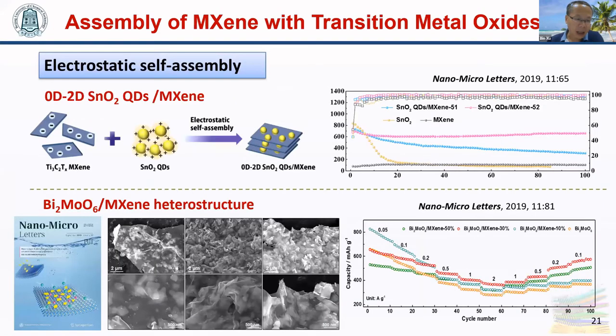As we know, MXenes are negatively charged, so MXene-based composites can also be easily prepared by electrostatic self-assembly, combining positively charged metal oxides with negatively charged MXenes. With this method, we prepared two materials. Both of them show very good cycle and rate performance.